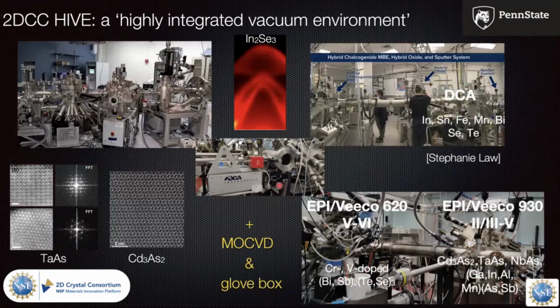This is not the only part of the facility. We also have an additional MBE system that was initially set up by Roman Engel-Herbert, but now it's run by Stephanie Law after Homan went to Germany. And it's also got my own MBE systems, which are a couple of VEECO systems. And here's where we grow cadmium arsenide, tantalum arsenide, and so on, as well as quantum anomalous Hall insulators. It's sort of dedicated towards that. And via vacuum suitcase, we can go in and use